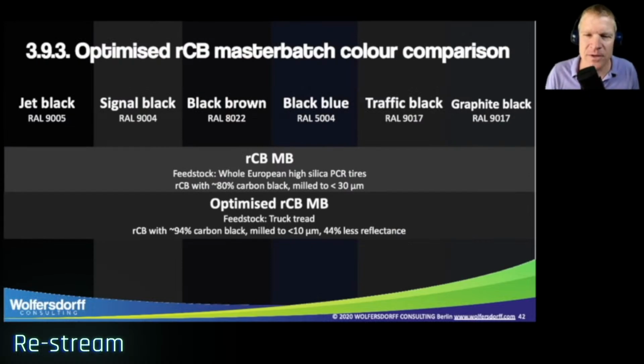Let's look at the optimized recovered carbon black master batch. So we said feedstock is pure truck tread. So we get an RCB with about 94% carbon black, which is very high. There's only 6% ash content or whatever, 5% ash content and maybe 1% moisture. This is milled to clearly below 10 micron. And what it results into, we have 44% less reflectance. Keep in mind, black is about absorbing the color and white or gray is about reflecting the color so that we can see it. And you can see already it is much darker.